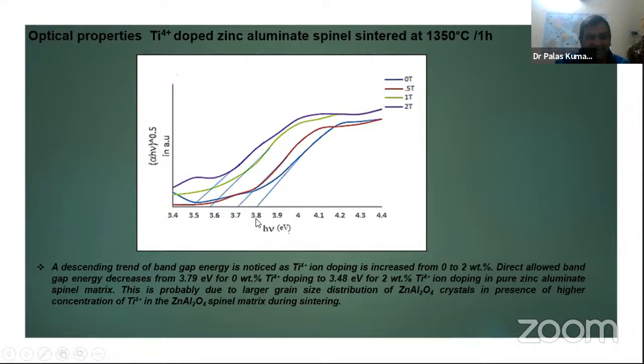So here we found that with increasing the dopant concentration, the band gap energy reduces from 3.8, the standard, and we also achieved almost the standard value 3.8 electron volt, and it is reduced up to 3.48. This is a very, very important thing, because this range, 3.4 to 3.5, is the band gap of gallium nitride. Gallium nitride is enormously used in the semiconductor field. So we are also getting, with titanium doping, a similar kind of band gap energy. It is 3.48. So this is quite significant, and we can say that for titanium doped zinc aluminate spinel, there is a direct allowed band gap.